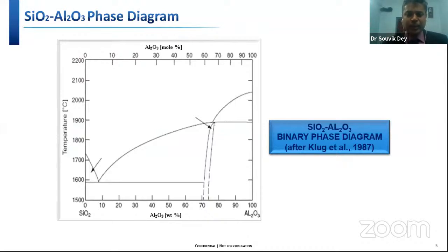So this is basically the silica alumina phase diagram. According to Aramaki and Rustum Roy, mullite melted congruently, that is, mullite melted directly to a liquid whose composition remained constant with an increase in temperature. A silica-mullite eutectic at 1595 degrees centigrade and a mullite-alumina eutectic at 1840 degrees centigrade were observed. Later, Klug et al. proposed another silica alumina binary phase diagram wherein incongruent melting of mullite at 1890 degrees centigrade and a shift of both boundaries of the mullite solution region towards higher alumina content is observed.